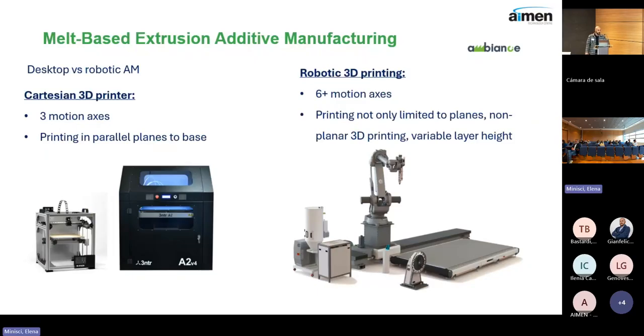Then on the motion systems, you have the usual Cartesian 3D printers that usually have three motion axes, and you tend to print in planes parallel to the base. There are experimental machines that overcome this limitation, but they are not on the market. You have the open 3D printers for processing PLAs, PETGs, commodity polymers that don't need high temperature chambers. The one on the right, the 3D black printer that we can see there, is a high temperature printer that is more focused on engineering grade polymers. And the difference is that you can set the chamber temperature just like an oven. So you have a temperature close to the Tg of the polymer during all the process, and you can prevent warping and thermal gradients during the process.